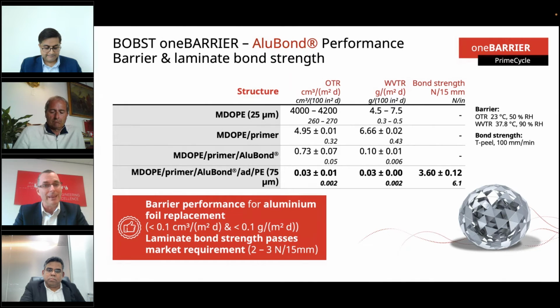With opaque Alubond metallization, we can enhance the OTR to about 0.7 cc's and the water barrier to 0.1 grams. And finally, with the same barrier adhesive and lamination to a very special 75 micron sealant web, we take the OTR and the water barrier to levels below 0.1, with a laminate bond strength of around 3.6 newtons per 15 millimeter. So in summary, with our opaque metallized one barrier MDO-PE structure, we've obtained a barrier performance equivalent to aluminium foil, and we also satisfy the market requirements for laminate bond strength. Next slide, Ben.